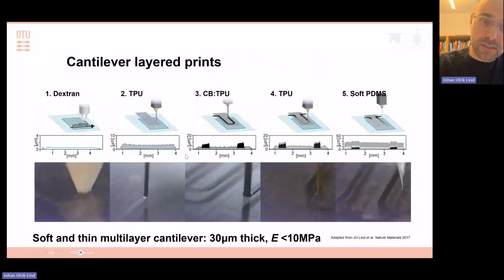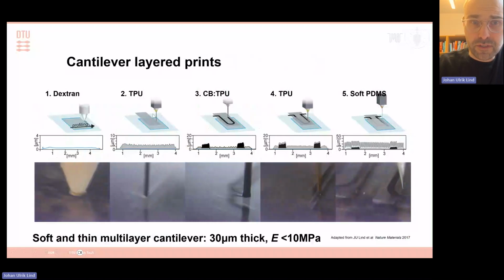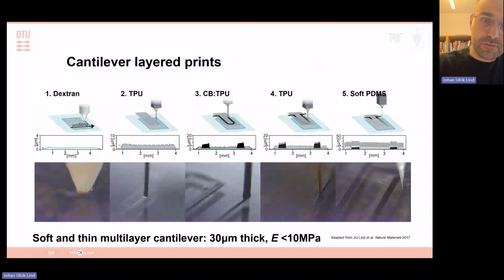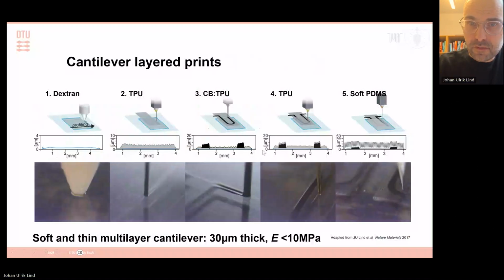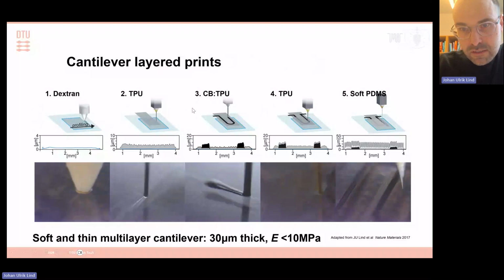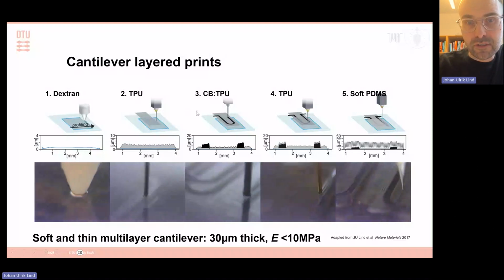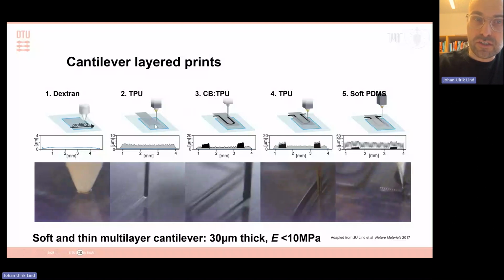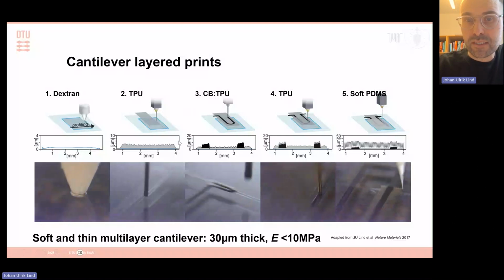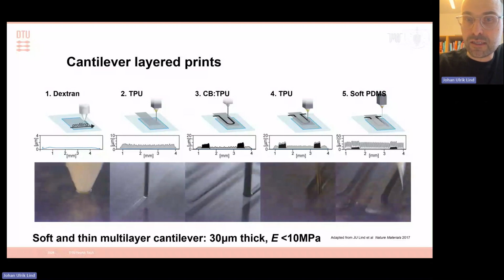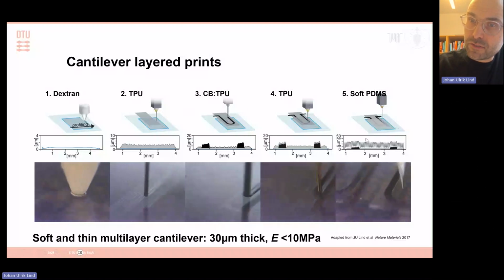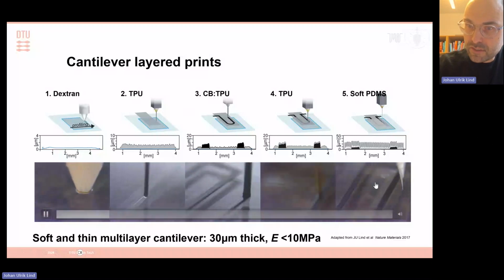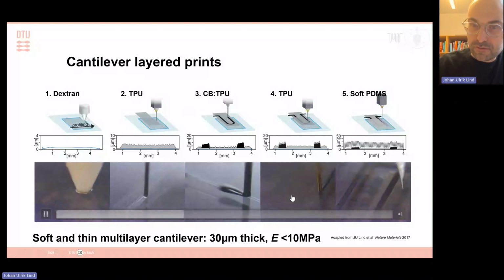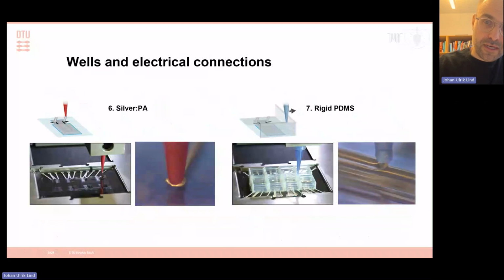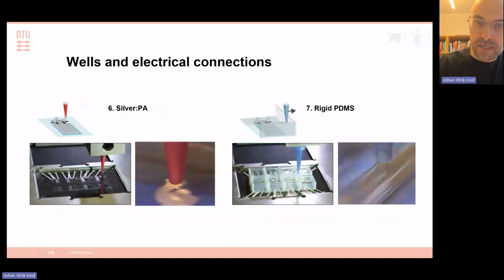So by having these dilute inks that solidify as soon as you print them and working with very close distances to the printer, you can print films that are easily in the order of microns. So down to single microns is not too difficult. Obviously you can't do high aspect ratio features, but what you can do is stack very thin films, which means that they are very deformable for bending in at least one direction. And then we add these grooves on top that I showed in the beginning. You can see these grooves being added here on top, taking a lot longer than just printing the cantilevers. You can incorporate that also with some printing of some housing, and then you have a fully printed device that takes about an hour to print.